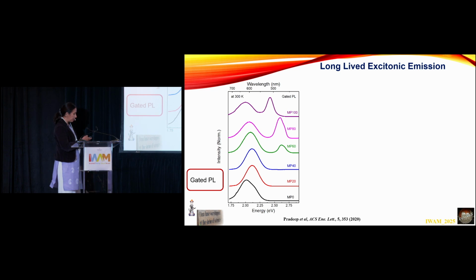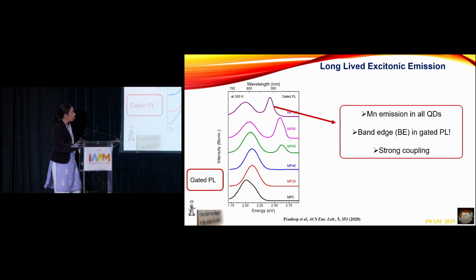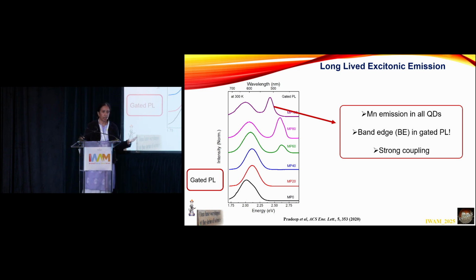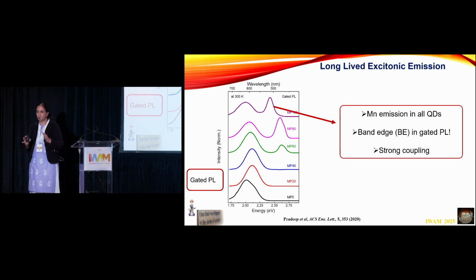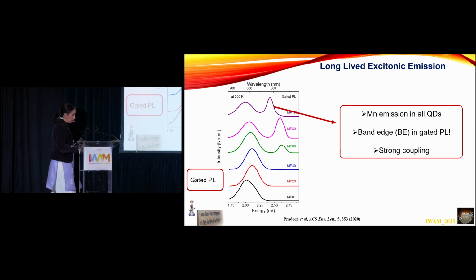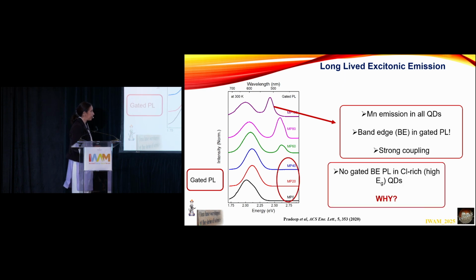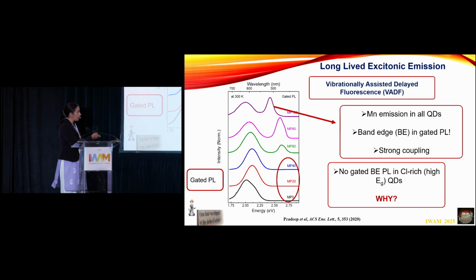But what is interesting is not just that this peak is there all throughout, which is not surprising, but the presence of band edge emission in gated PL. This suggests that band edge emission is extremely long-lived. Typically in undoped systems, they tend to decay within a few nanoseconds, and they have no business to be here in a few microseconds time. So this suggests that there is a strong coupling of the manganese with the band edge emission, and it's also very sensitive to which compound you're using. For example, in the chloride setup, you do not have it, but in the bromide setup, it is very, very strong.